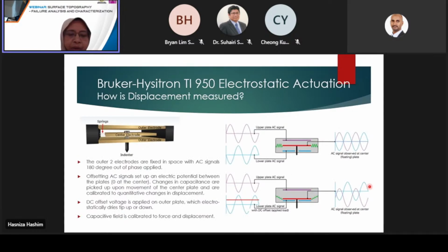Now, let's look at how the force is actually applied and how displacement is measured. In our system, the probe is installed into the floating metal plate of a 3-plate capacitive transducer. The displacement is measured by running two AC signals, 180 degrees out of phase with each other, to the top and bottom of the 3-plate capacitive sensor. The AC signals are observed by the center plate, and the sum of the signal corresponds to a measured displacement. To apply load, a DC offset is applied to the lower plate of the transducer, which electrostatically attracts the center plate downward.